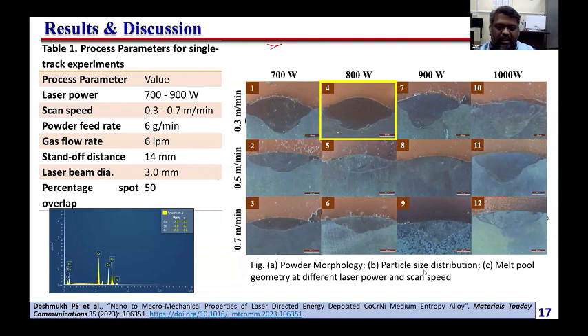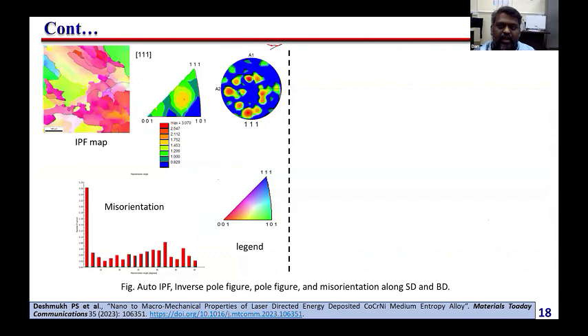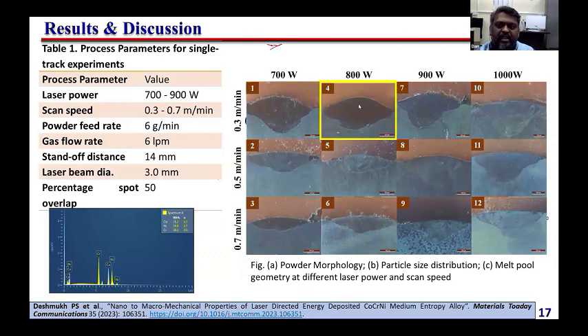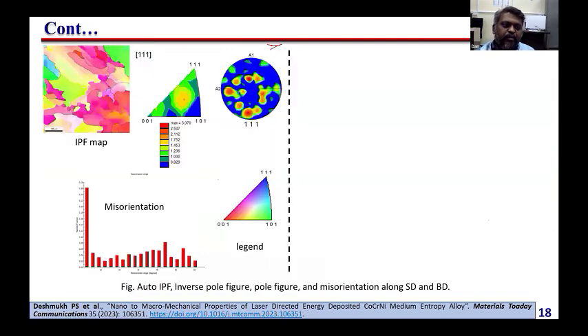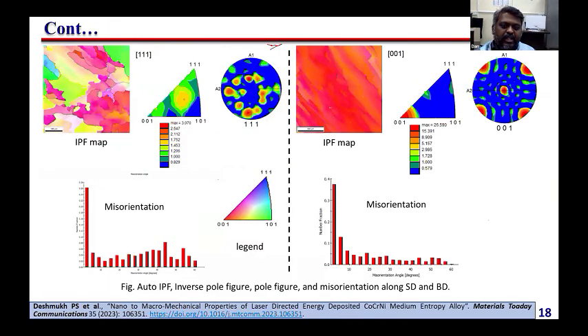Based on the porosity and the bead height aspect ratio, we decided that the fourth parameter set gives a better bead height and width, and the porosity levels are much lower in this condition. So with that laser power and scan speed we went on to the deposition, layer by layer.